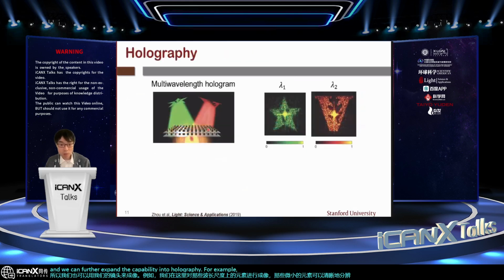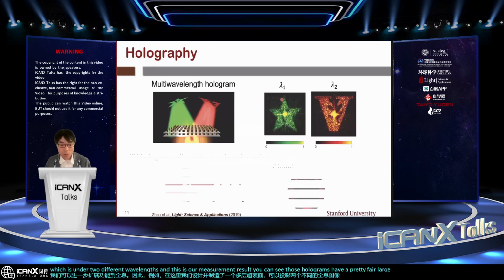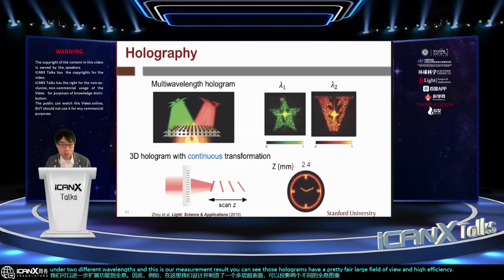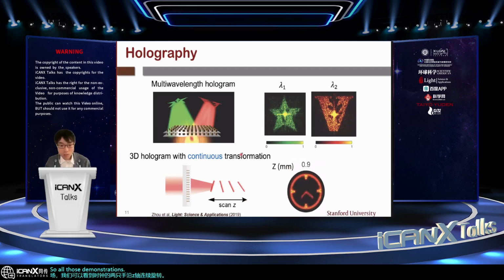For example, here we designed and fabricated a multi-layer metasurface which can project two different hologram images under two different wavelengths. And this is our measurement result. You can see those holograms have a fairly large field of view and high efficiency. And we can also expand its capability into complex three-dimensional light field control. In particular, I designed this 3D hologram encoded with continuous transformation. This means that as I'm scanning the far field, we can see the two hands of a clock continuously rotating along the z-axis. All those demonstrations show the extended capability of this new design freedom.